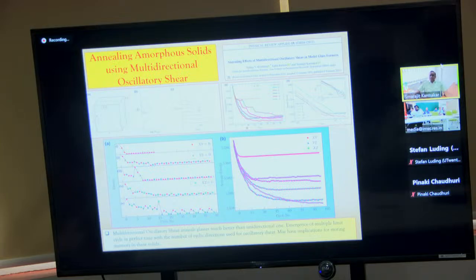But what is most important and interesting is that for the better annealing procedures, although the phase diagram remains very, very similar, there also you have an energy scale below which you can no longer anneal your sample using the oscillatory shear protocol. So mechanical annealing seems to have a lower bound. This lower bound is a fundamental question which, as I said, nobody has an answer to, and which remains an open question. One interesting thing that we found is that if you do a random sequence of oscillatory shear, then your energy profile goes down, down, down, and it takes an enormously large number of cycles to reach a steady state. This explores various complex paths of the minima, and then eventually will saturate at some point because the phase diagram doesn't evolve beyond this.